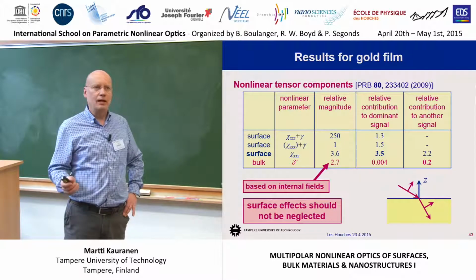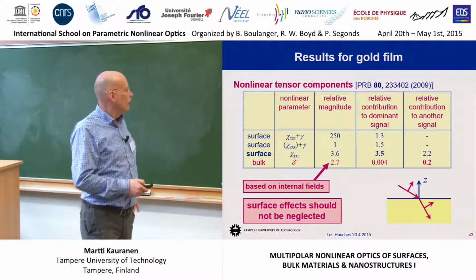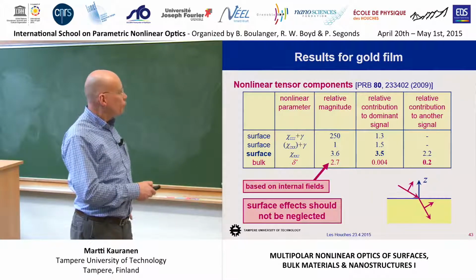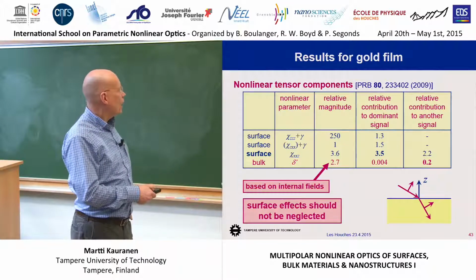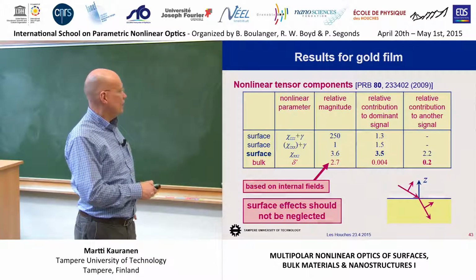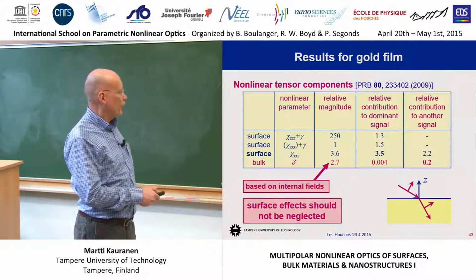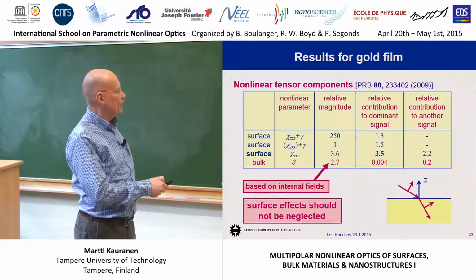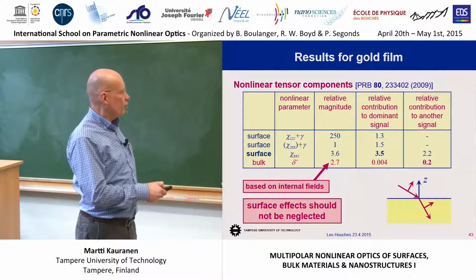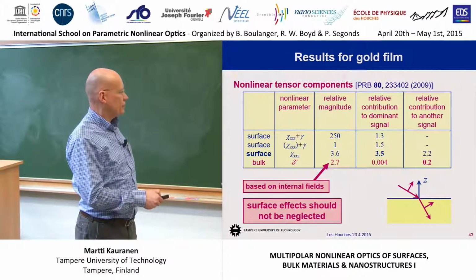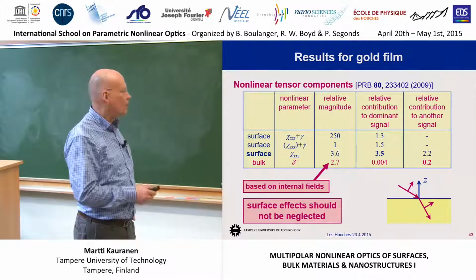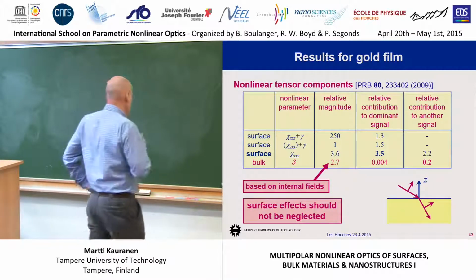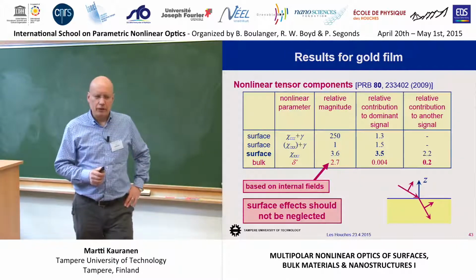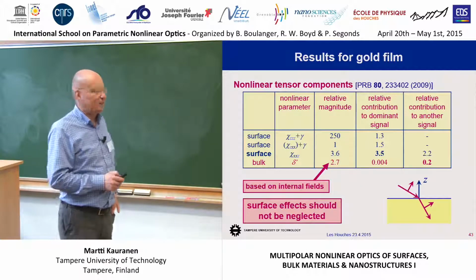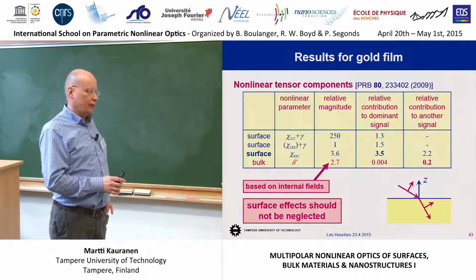In the end, you measure signals and not direct tensor components. And then things change completely. The dominant contribution to our signals comes from the surface component XXZ, and then the bulk parameter becomes relatively really weak. But this is how it contributes to the dominant signal. If you look at other signals that we measure, then the bulk contribution becomes reasonable already, tens of percent and so on. So the point is that when you're doing surface nonlinear optics, and especially mixing in the bulk effects, you have to be really careful how you interpret the results.